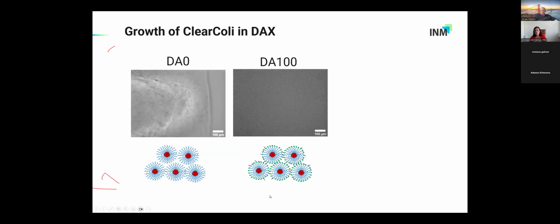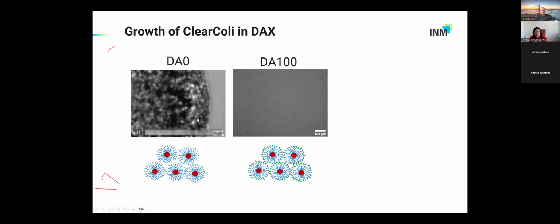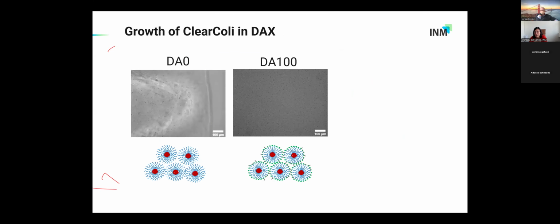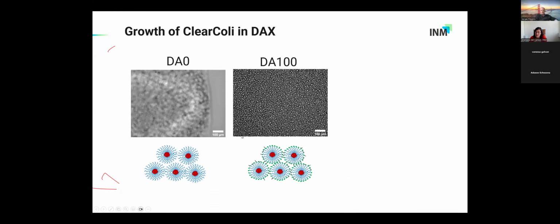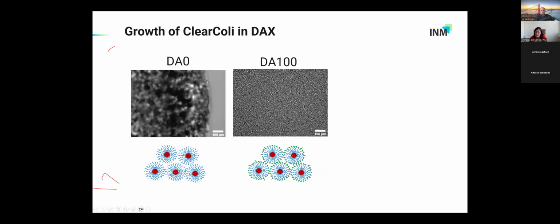Now with these hydrogels, if you put bacteria in these hydrogels, you see the following. If you put them in the physical hydrogel, the one with the lower shear modulus, you would see that bacteria actually grow very fast and fill the whole hydrogel. They actually outgrow the hydrogel as well, sorry. Whereas if you do this with the hydrogel, which is heavily chemically cross-linked, bacteria also grow, but they grow much less. You see here they form small balls, small colonies, and they stop growing. They would never outgrow the hydrogel. I run the videos again so that you see the difference. Here they grow out, here they stay in.